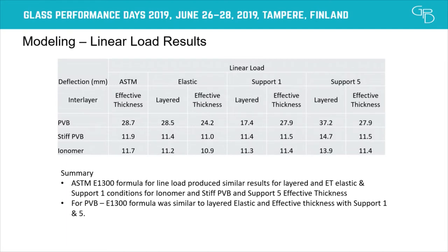For the linear load, it was pretty much the same as the concentrated for the stiffer interlayer, stiff PVB and ionomer. They were all pretty close, except for the layered support 5. For the softer PVB, they were pretty random. But the effective thickness method from ASTM for PVB matched the layered elastic and the effective thickness support 1 and effective thickness support 5. So there were some similarities there.